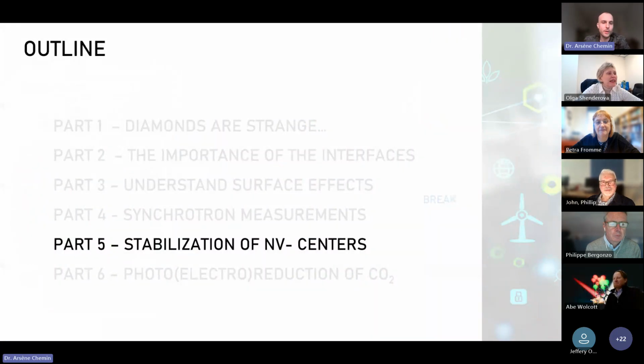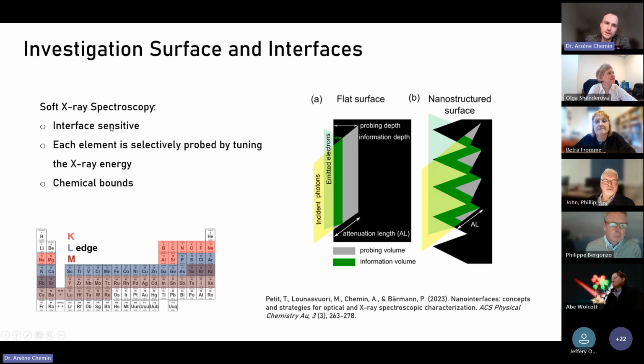So I will talk about the stabilization of NV centers and some synchrotron measurements with that. Very briefly, the idea of doing synchrotron measurements is that by looking at the X-ray, we can be very interface sensitive because the X-ray, especially in the soft range, will attenuate very fast in the material, within a few micrometers. On top of that, what we are often probing is the emission of electrons from those photoexcitation. And those electrons will be emitted from only a few nanometers. So this is why X-ray are so interesting. We can probe only a few nanometers.